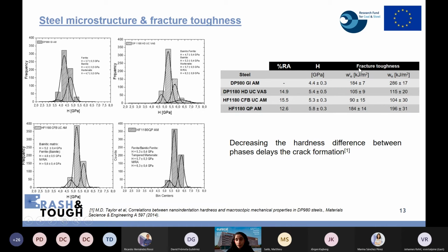If we compare the fracture toughness at crack initiation, these results are from the essential work of fracture. We can observe that if the hardness difference of the microstructural constituents is smaller, this fracture toughness increases. So the best results are for DP, the first generation grade steel dual phase, and for the QP, because the difference between the microconstituents is smaller. This is because decreasing the hardness differences facilitates enhanced local formability.